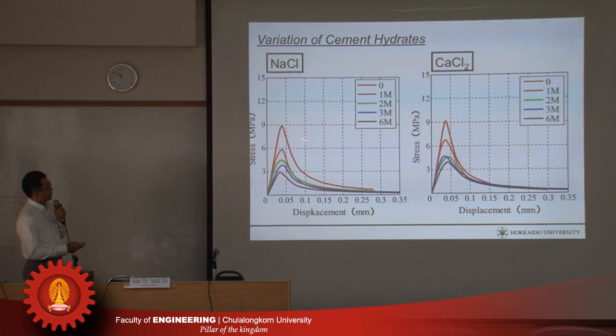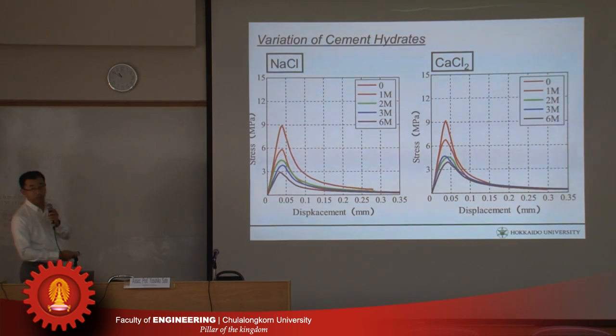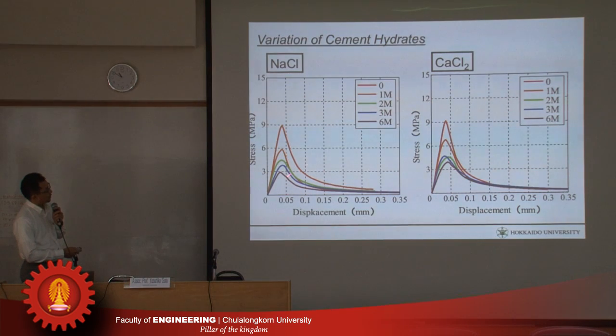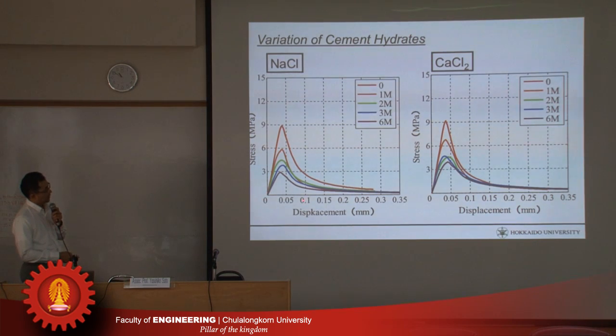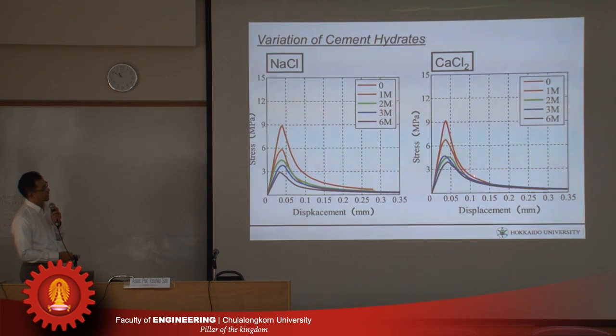This is sodium chloride and this is calcium chloride. The change in strength is almost the same, but the softening branch is totally different. The amount of chloride itself is the same in the immersion test, and the strength change was also the same, but the softening branch was totally different.